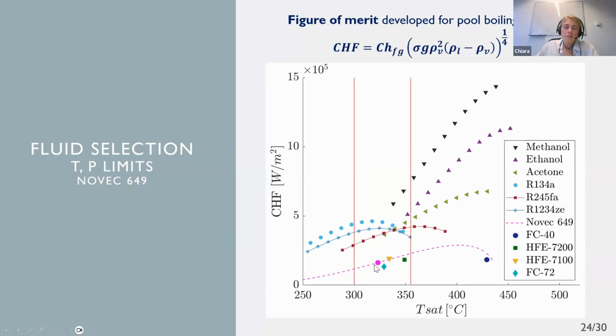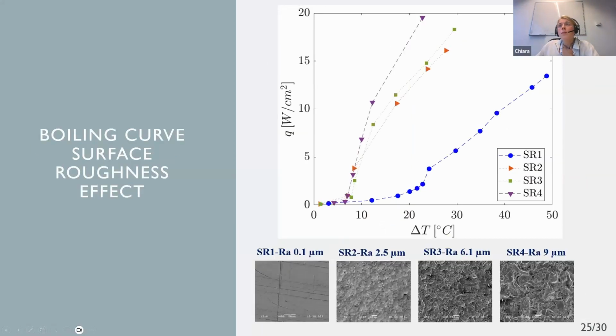So among different NOVEC refrigerants, we decided to go for NOVEC 649 because it has a saturation temperature, indicated by this dot, of around 49 degrees at ambient pressure. And it has a very low global warming potential, below 1. So that was also something that we had to consider. Now I'm going to show some heat transfer results of NOVEC 649 for the surfaces with different roughness.